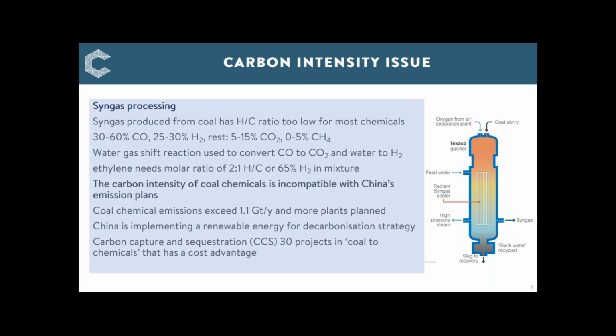The syngas that's produced is largely carbon monoxide, 2 to 1 on hydrogen by volume typically, with CO2 and methane also present. And the water gas shift reaction is then used to convert CO and water to CO2 and hydrogen. In that way, you raise the hydrogen content of the gas. And for methanol, we need at least 2 to 1 hydrogen to carbon monoxide. So you can now see where the 3 to 1 ratio comes from: because of the original carbon monoxide in the syngas, 2/3 must be converted to get the right ratio, and that is then released as carbon dioxide.